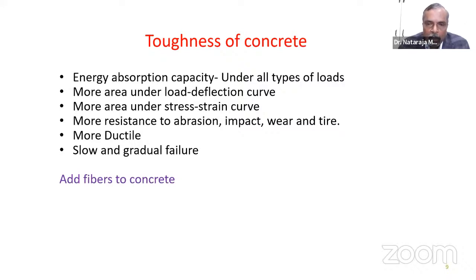As you know, the normal concrete is really not going to perform well because it is highly brittle in nature. And many people are under the impression that as the strength of the concrete increases, many of these toughness related properties will increase. There might be a small improvement in the toughness, but the rate of increase in the toughness, the rate of increase in the energy absorption capacity, is not in the same ratio as the compressive strength of the concrete is increasing. So when you take, say, M40 concrete, when it is compared with M20 concrete, the toughness may be slightly better, but not that the toughness of the M40 concrete is increasing almost by 100%. So unless we add some additional materials to the concrete, it is extremely difficult to increase the energy absorption capacity of the concrete. So this is where the use of fibers plays a very important role.